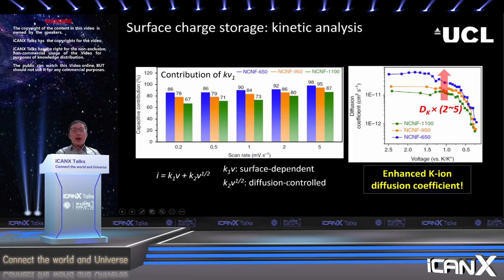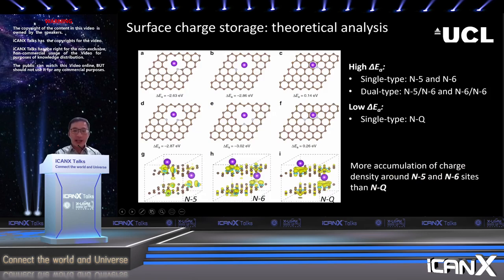We also used simulation as a further evidence to explain why we can obtain such a good potassium storage performance from the 650 degrees materials. What we did is we simulate the absorption energy between carbon structure with different types of defects, which is caused by the different types of nitrogen doping. And we compare the absorption energy between the different carbon structures and the potassium ions.